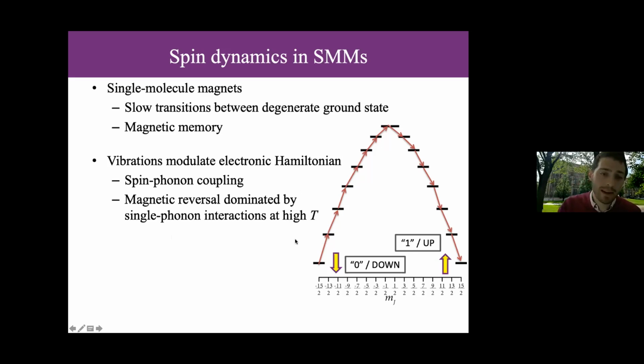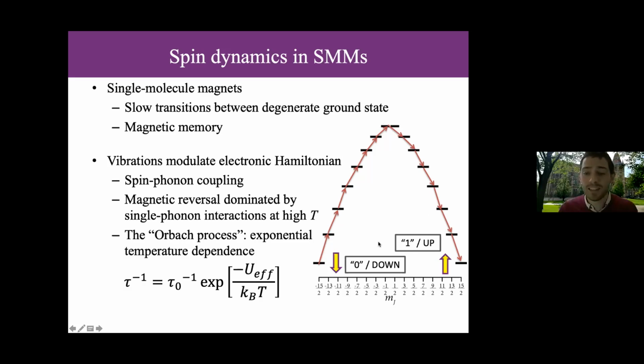And so for single molecule magnets at high temperatures, we talk about relaxation occurring over a barrier via the Orbach regime. And so at high temperature, these dynamics are dominated by spin phonon, single phonon interaction. So these are either single phonon absorptions, where the molecule is gaining energy and absorbing vibrational energy from the lattice, or emitting as we go down the other side. And this leads to this concatenated process of multiple single phonon absorptions and then emissions is what is known as the Orbach process.